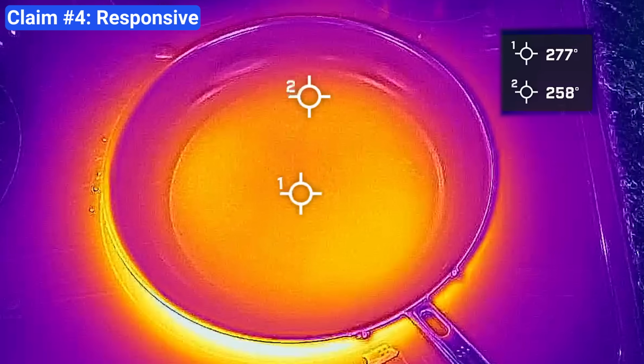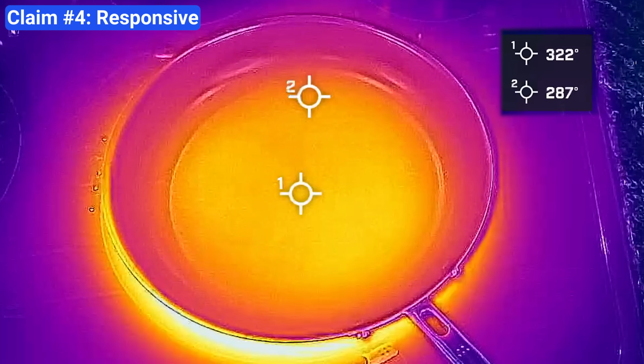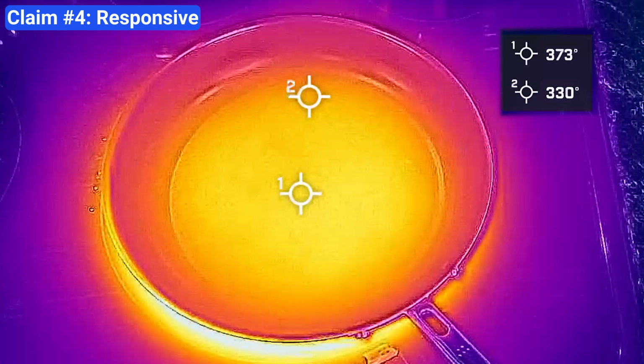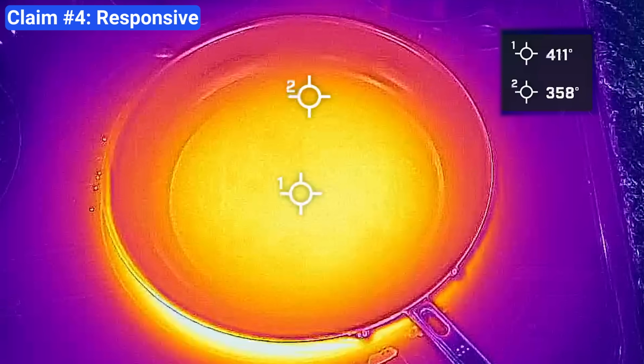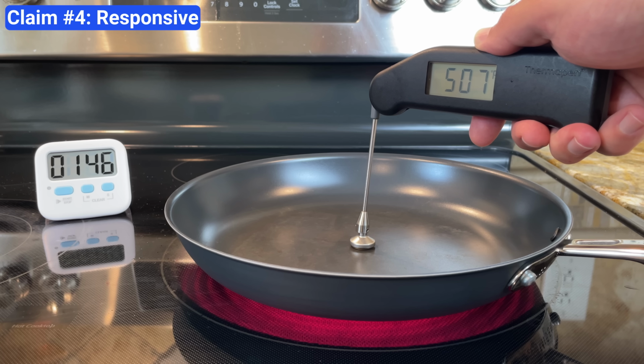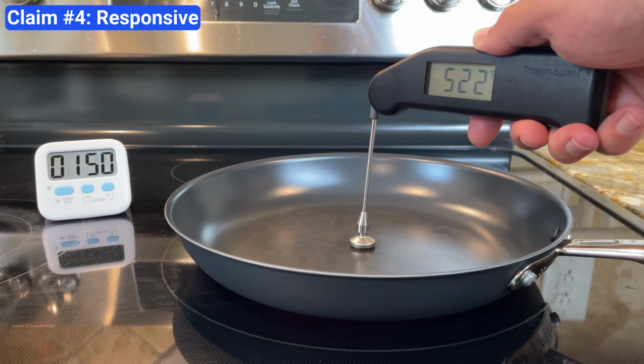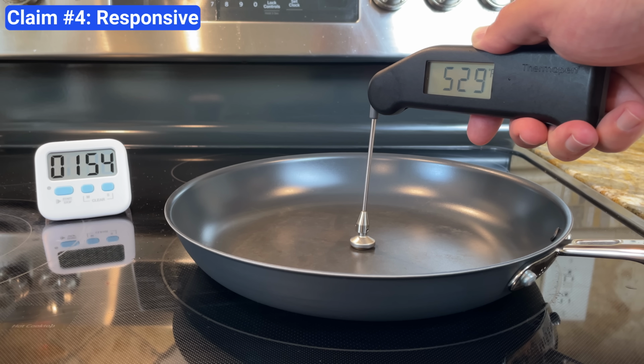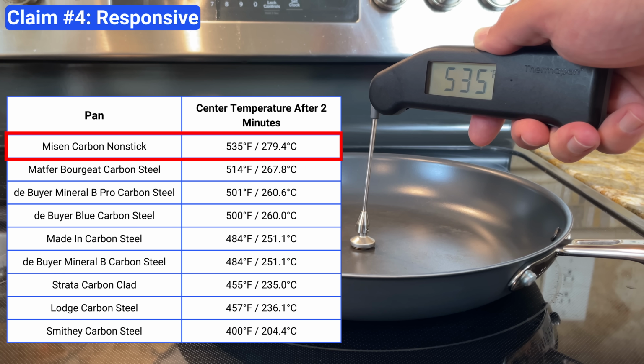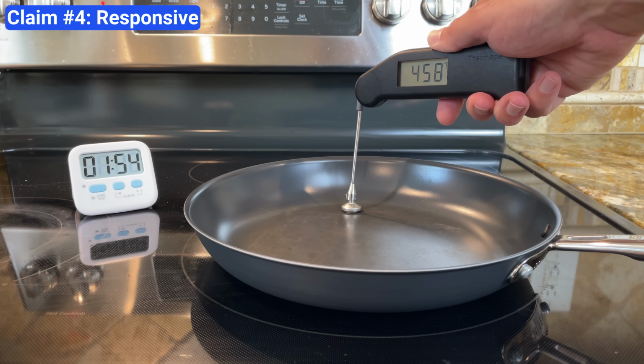Another claim Misen makes is that this pan, due to the aluminum core, is more responsive to temperature changes, which makes cooking more efficient and precise. To test that, I heated the pan on medium and measured the surface temperature after 2 minutes, the same way I test every pan I review. And the results back up the claim. The Misen pan heated up extremely fast. It was the fastest carbon steel pan I tested, and the second fastest pan across all materials. I also measured the temperature at the edge of the pan.